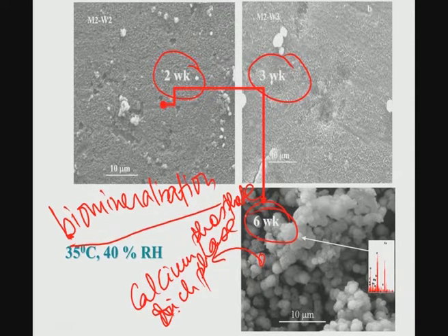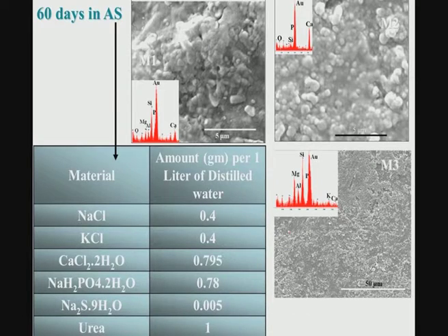Why? Because your natural bone or hard tissue is also mineralized tissue, right. And so, when cells see a material surface where there is a mineralized layer formation, automatically there will be better compatibility with the natural osseous structure. I hope I have emphasized this point enough so that you understand that it is possible for a material, even without containing calcium oxide or some of the precursors of calcium phosphate, to indeed form calcium hydroxyapatite when dissolved in artificial saliva, for example.